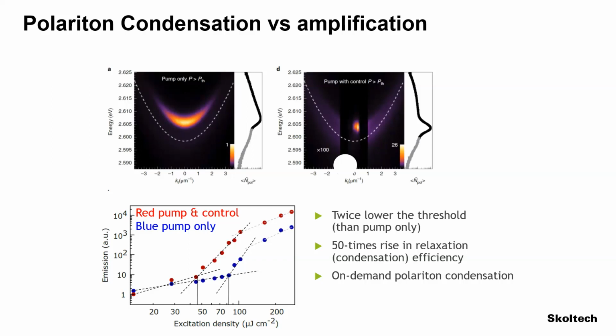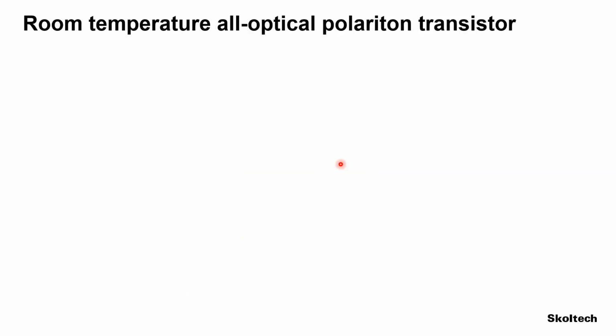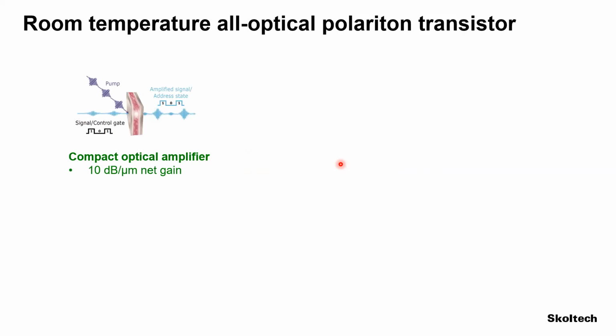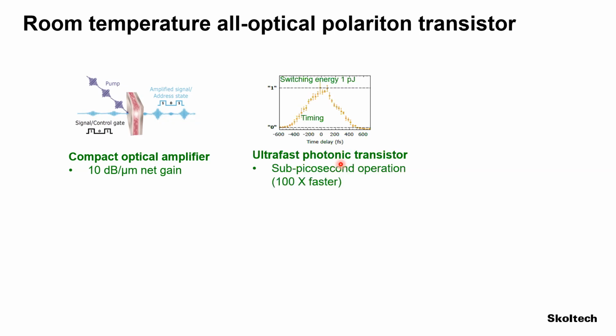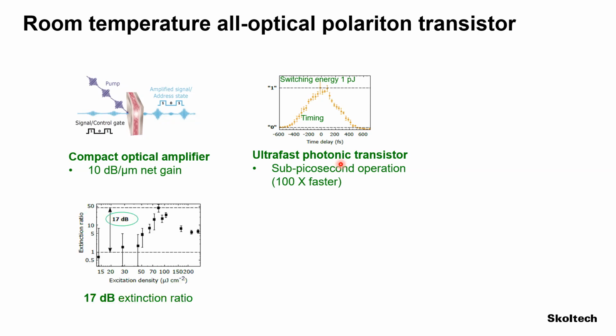So by doing that, we could really put together all the characteristics of a transistor, so we could demonstrate that we can amplify the control beam, and we can report amplifications that reach 10 decibel per micrometer net gain. This is some of the highest nonlinearities ever reported, and the fact here is that we are using the process of polariton stimulation through the vibron emission. Then we could show here that the time it takes to switch the system on and off is sub-picosecond, yes, with a switching energy of 1 picojoule at that time. Then we could show that we have an extinction ratio between the on and the off state of up to 17 decibel, which is actually a very good number for optical differentiation of an on and off signal.